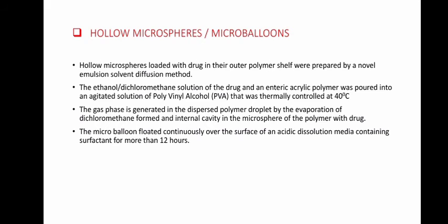The gas phase is generated in the dispersed polymer droplet by the evaporation of dichloromethane, which formed an internal cavity in the microsphere of the polymer with drug. The microballoon floated continuously over the surface of an acidic dissolution media containing surfactant for more than 12 hours.